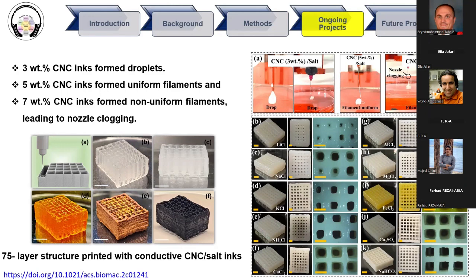This is the reason why 5 weight percentage of cellulose plus salt is so important. It's the best candidate for our samples. We continued our research based on these samples, 5 weight percentage of cellulose plus 25 to 100 millimolar salts. From the left side of the slide, we can see the schematic of a 75-layer structure printed with conductive CNC salt inks. In B and C, we have just cellulose without any salt or conductive part. In D, we incorporated the iron-based salt. We also used a freeze dryer to dry it. From E, we can see a dried 3D printed sample. And F is the conductive one, made by adding conductive polymers.